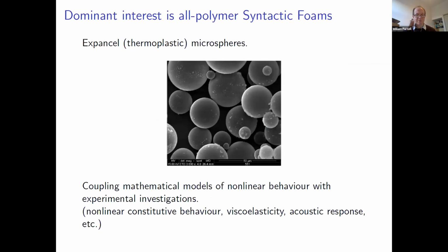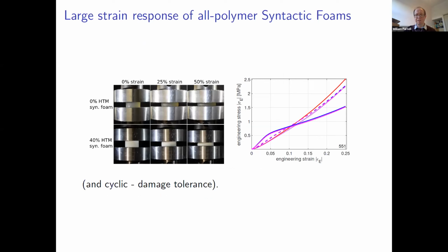So our main interest in terms of syntactic foams is all polymer syntactic foams. In fact, when microspheres are these Expancel (thermoplastic) microspheres, we try to couple mathematical models of nonlinear behavior with experiments, and we're critically interested in nonlinear constitutive behavior, viscoelastic response, and the acoustic response. And so we're interested in being able to model this kind of complex nonlinear behavior that arises in these syntactic foams, usually associated with the complex buckling and interaction of the microspheres within the composite material.